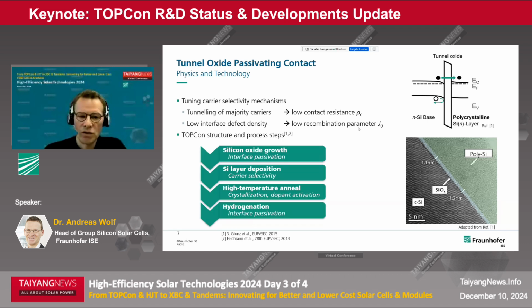And usually the fabrication of the structure consists of these 4 steps. You first grow the interface oxide, then you deposit the silicon layer, which might be either doped already or undoped. In the subsequent step, the layer is crystallized, dopant is activated, or it's provided if the layer was deposited undoped. And finally, a very important step is providing hydrogen to the whole system to passivate any main remaining defects.